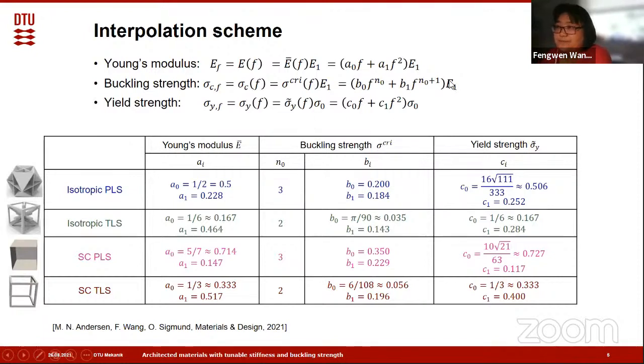For uniaxial compression, an interesting thing I would like to point out is for buckling strength, as one can see, plate structures have a higher order volume fraction dependency compared to a truss lattice. This indicates that at a low volume fraction, truss lattice shows higher buckling strength. However, if we go up to moderate or even higher volume fractions, plate structures will show higher buckling strength because of the higher coefficient. So now the question is whether we can find some macrostructure configurations which can show a tunable stiffness and buckling strength performance.